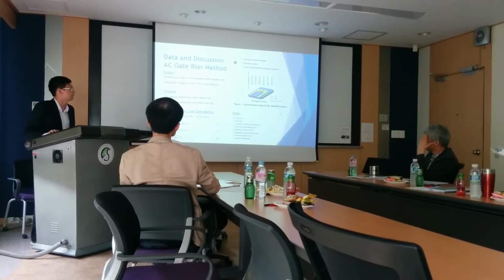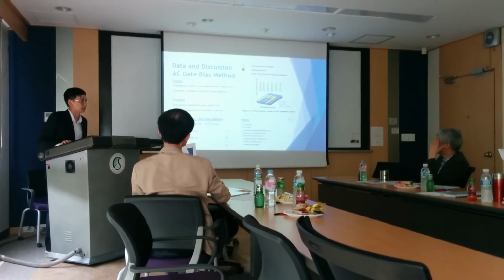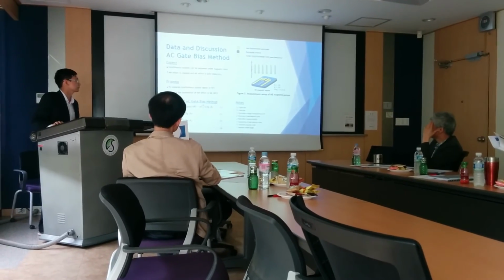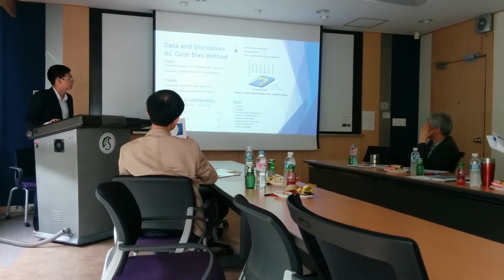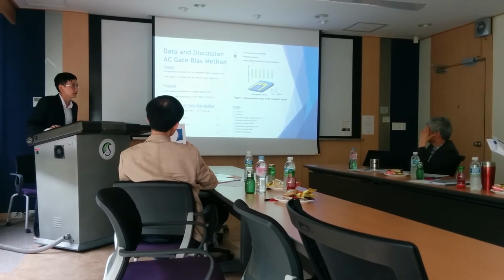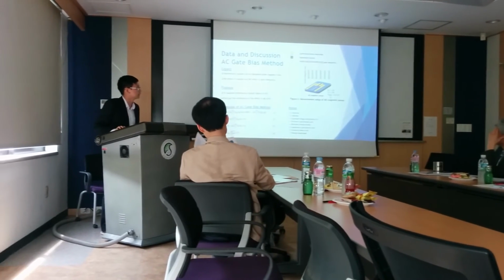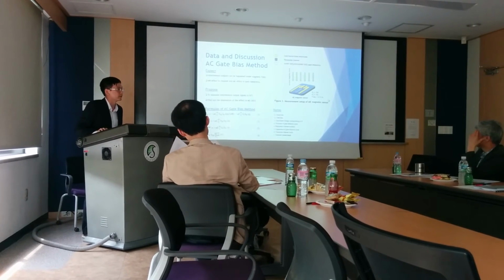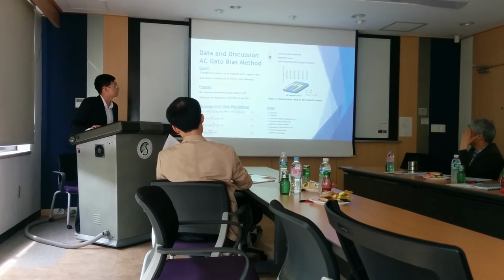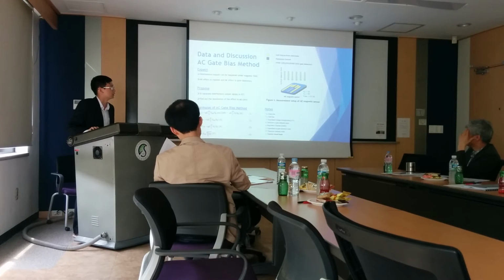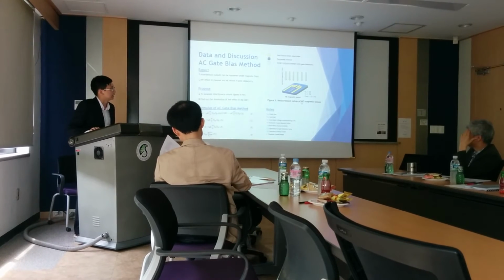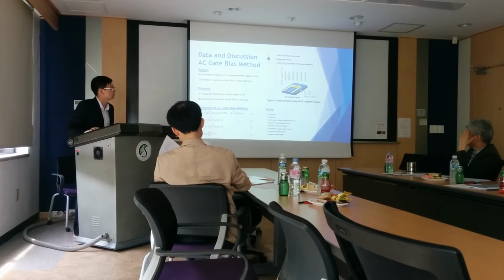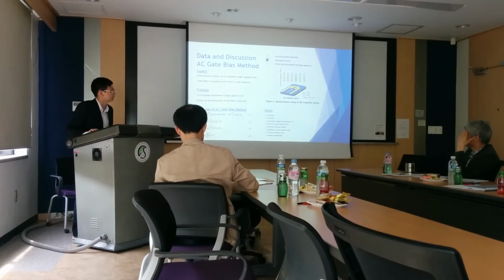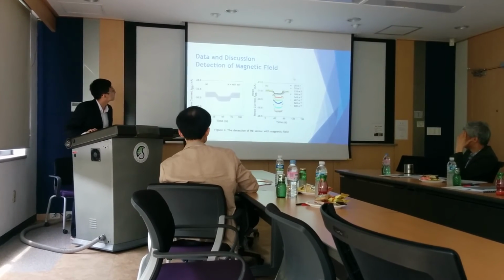This is the measurement setup of the ME magnetic sensor, as you can see in figure 3. Drain and gate voltage were fixed at -5 V, and the frequency applied was 0.5 Hz. The vertical magnetic field was applied directly on the ME magnetic sensor, and the intensity is changed by the distance between the sample and the magnetic field source.